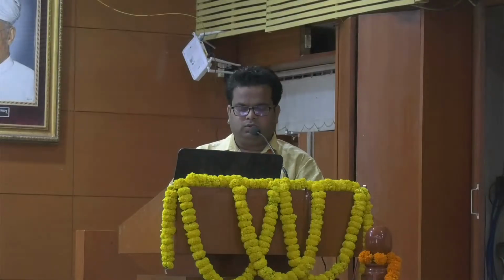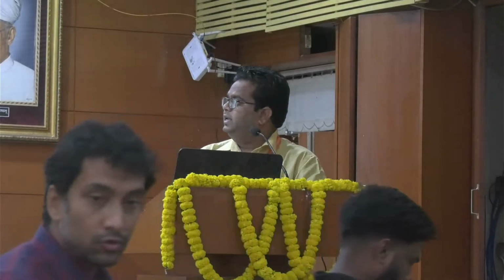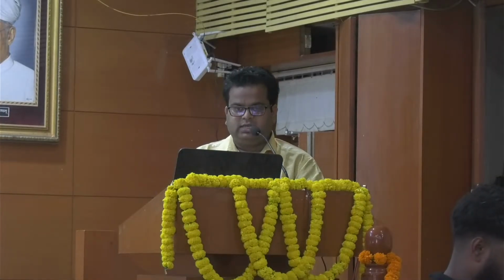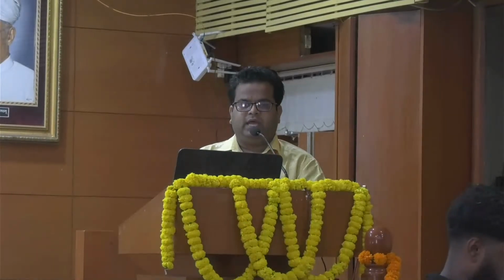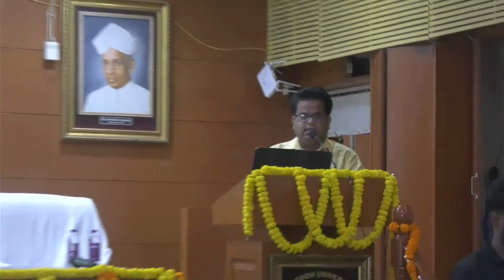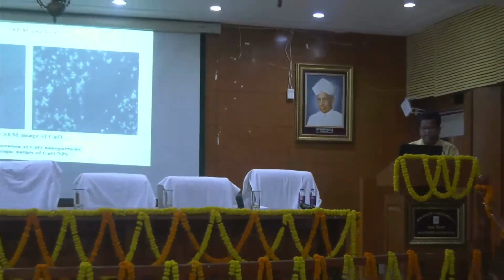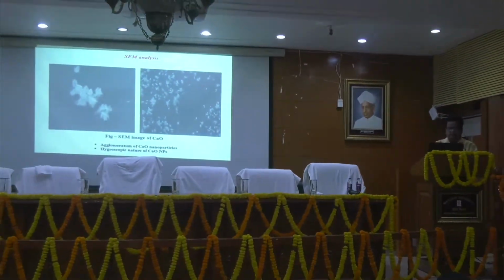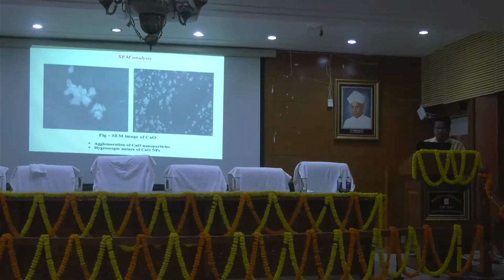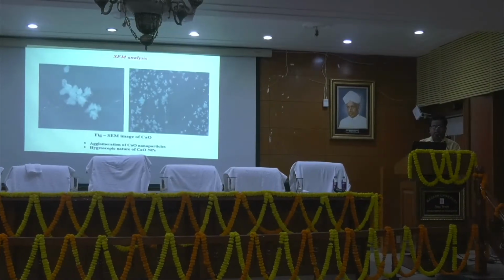Again we have gone through the same analysis, where we can see that calcium oxide is agglomerated in our experiment. We suggest that calcium oxide is hygroscopic in nature, and when we are reducing particles to nano size, the surface area to volume ratio increases, which increases the reactivity, and that's why our calcium oxide nanoparticle is agglomerating.